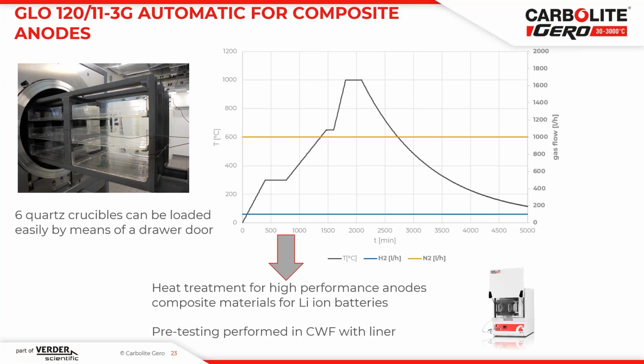And there some pre-testing was done. It worked okay, but this furnace is mainly not made for pyrolysis because the exhaust of this small furnace is very, very small. So there are some issues that lots of binder and pyrolyzed materials can condense, and then the gas outlet, the exhaust, gets stuck. And this is really not good for the process if you have an overpressure. So lots of things can happen.